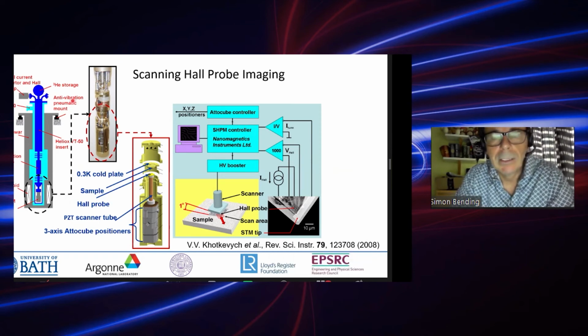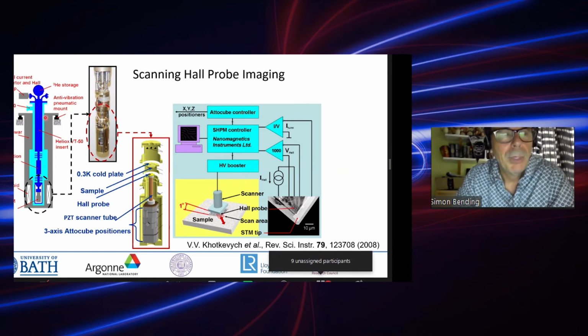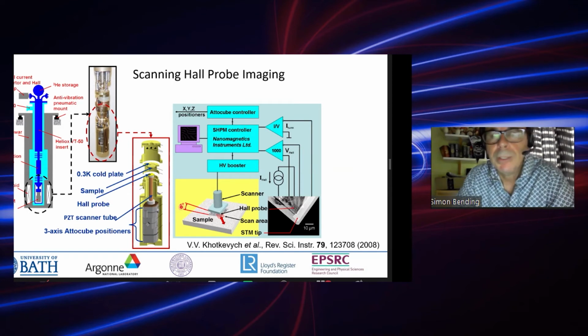Oxford Instruments Heliox helium-3 fridge put inside a helium-4 cryostat. And really the important part, the sharp end, if you like, of the microscope is sketched here, where we have a sample which is firmly anchored to a 300 millikelvin cold plate up here. The Hall sensor approaches from below. It's manipulated by a triple-axis Attocube micro-positioning stage, which gives us our coarse motion, and then our fine motion and scanning is provided by this piezoelectric tube. It's quite a long one, a 2-inch piezoelectric tube.